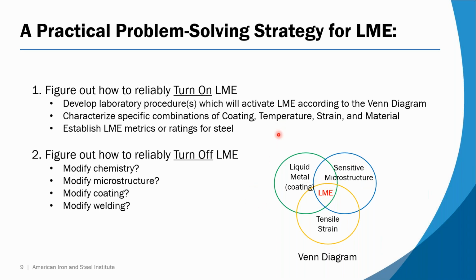And then if we're successful at that, then we leave it up to others to maybe turn off LME. What could you do? You could modify the chemistry of the steel. You could modify the heat treatment or the microstructure of the steel. You could modify the coating. You could even modify welding.